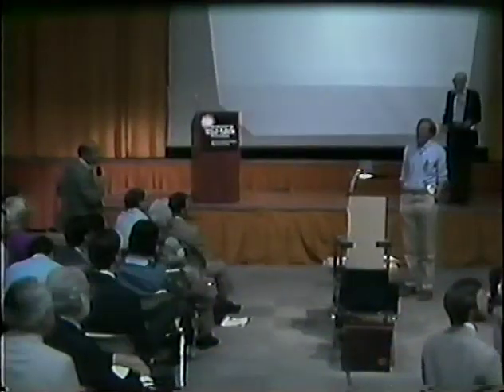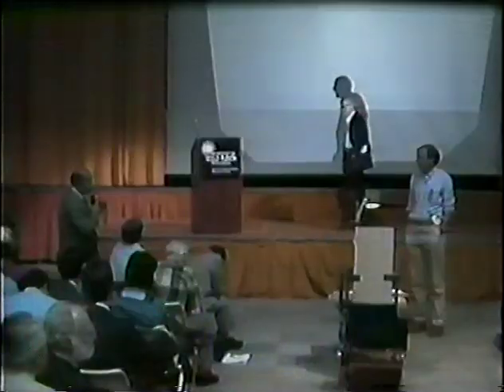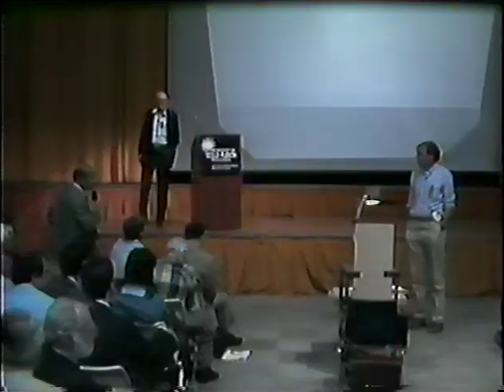Norm Goldstein, Westinghouse R&D. What is the form of your film? Was it amorphous? It's initially crystalline. We've taken similar films and done X-ray diffraction on them, and after the same kind of bombardment, the X-ray diffraction gets a little sloppy, as if there's a certain fraction of amorphous, but there's still a dominant crystalline component even after the bombardment. Okay, so that's what I was really leading up to. You don't think the radiation damage has a major effect then? It might play a part. All right. Thank you.